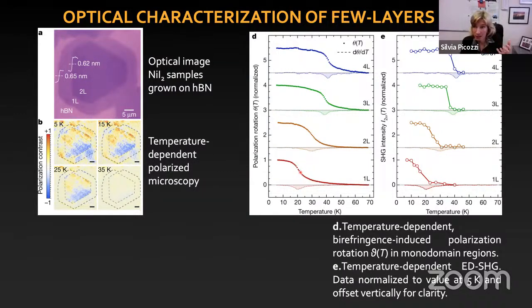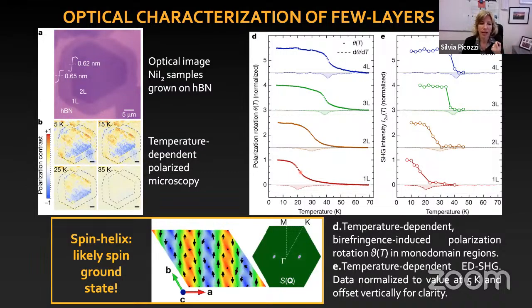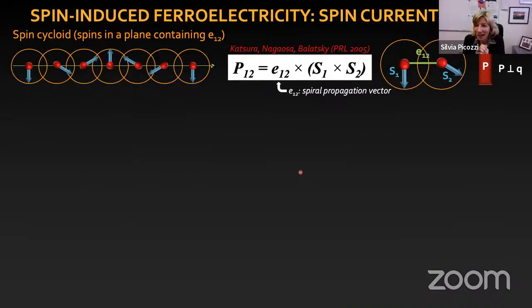And so we thought, okay, maybe a spin helix has a ferroelectric polarization. So let's calculate the spin helix and whether it has a ferroelectric polarization. But of course, we know since a long time that there is a basic mechanism to explain polarization driven by complex spin order. And this is due to Katsura, Nagaosa, Balatsky, also the Mostovoy picture. So what it says is that if you have a non-collinear spin texture, so you have, for example, a spin 1 and spin 2 with different directions, then they give rise to a dipole, and one can write the dipole in the following way.